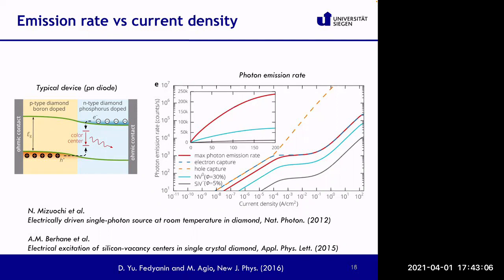Then, of course, it depends on the quantum yield of the quantum emitter. So you see here for the nitrogen vacancy, if you take 30% quantum yield, you get a curve. If you go to 5%, which we assume for the silicon vacancy, you get a lower emission. So overall, the emission rate is not very exciting, because you need to have a very high current density. We are talking about 100 amperes per square centimeter to get 10 to the 5 photons per second. However,